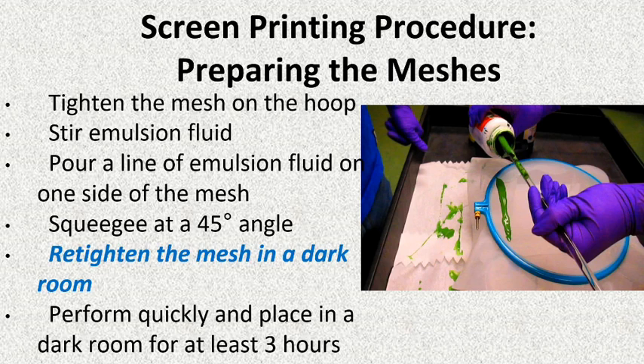Then, this is a step that we added this year. Once you have applied the photo emulsion fluid, you are to retighten the mesh in a dark room. This eliminates any chance of warping or folding or bending in the mesh, and it significantly improved the amount of meshes that we made. And you are to perform this quickly and place in a dark room for at least 3 hours. Overnight is better. The reason that you want to do this is because, as I mentioned, this is photo emulsion fluid. It reacts to light. We do not want it to react to light until we are ready for it to react to light. So, perform quickly and in a dark room.